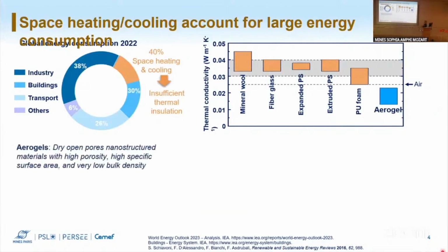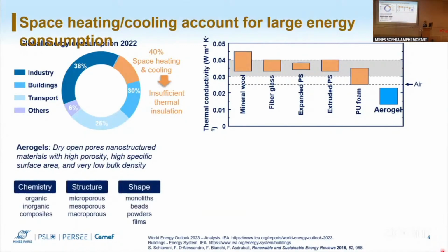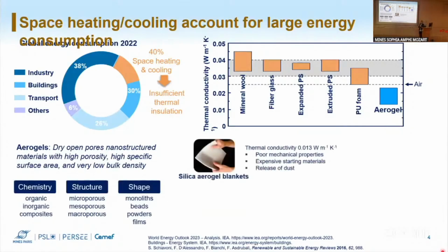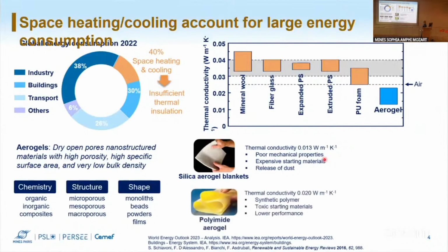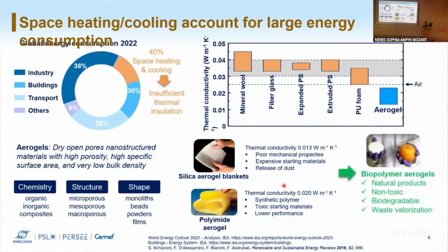What are aerogels? Aerogels are open pore nanostructural materials that have high surface area, they have very low bulk density, and they have a very high content of porosity. They can have different chemistry, structure, and shapes. And right now we can find commercially available, not in the neighborhood store, let's say, but we can find silica aerogel blankets that have the lowest thermal conductivity. The lowest thermal conductivity that is available for commercial products is 13 milliwatt per meter Kelvin. However, they are very expensive and they have poor mechanical properties. And for this reason, more lately, synthetic polymer aerogels were fabricated to overcome these problems. However, they have a bit lower performance, so higher thermal conductivity. What we want to do is to pass to biopolymer aerogels, so to have natural products that are non-toxic, biodegradable, and come from waste for valorization.